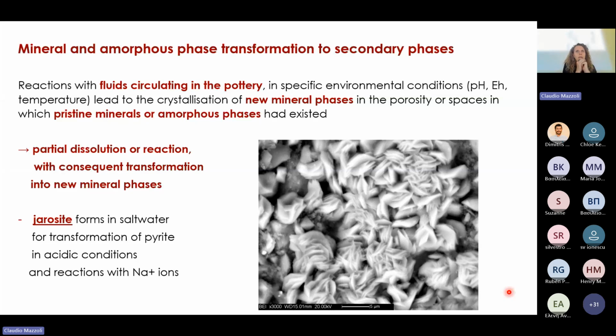Another type of secondary phase that can form is, for instance, jarosite. This mineral phase did not form by simple precipitation, but derived from a transformation of a pristine phase into a new mineral phase, right? So we normally have a partial dissolution or reaction with a subsequent transformation into a new mineral phase. These are very complicated processes. What I'm telling you is that it's not simply a precipitation into porosity, but a transformation of a mineral into something else, into a new mineral phase.